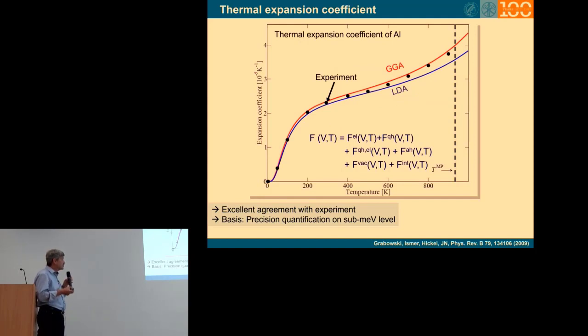So in order to really come to methods which allow us to describe these type of properties, we have to push to the precision of this one milliEV level, but we also have to include a lot of extra physics. So you have to look into electronic excitations, quasi-harmonic excitations. Typically we have to go well beyond the quasi-harmonic excitations so that we have all the anharmonicity in there. Electron-phonon coupling becomes important, impurity become important.